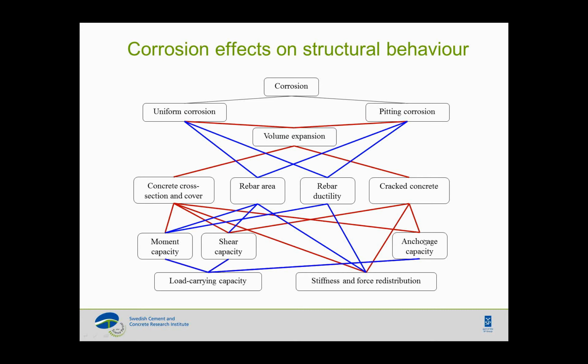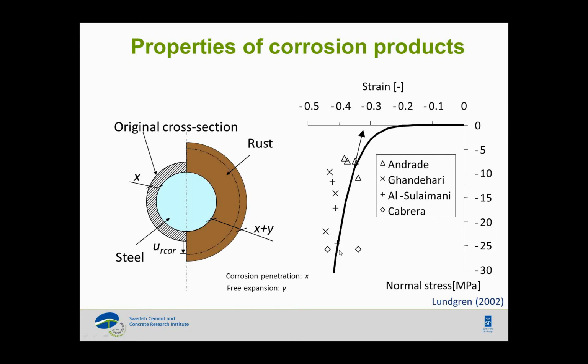What we do in the model is that we actually have implemented the swelling effect of a corrosion product into a subroutine which is coupled with our structural analysis that we carry out with Diana. What are the most important parameters when you try to run such analysis is the material properties of corrosion products. It's really important to have an estimation of the material properties of rust. So in this case we have been trying to look at different experiments and trying to run analysis and see what it is that best describes properties of rust.